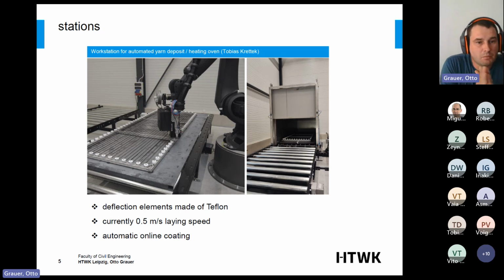During this yarn placement, the carbon yarn is impregnated online with a resin matrix. This binds the individual carbon fibers or filaments together so that the complete reinforcement cross-section of the yarn used can be applied in the static analysis. In addition, the impregnation supports the position and the stability of the reinforcement mats during concreting.